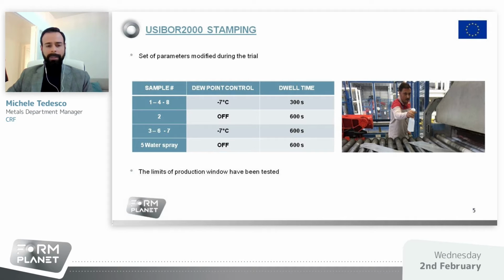component. Based on that, we would like also to test the worst condition that is indicated as number 5, in which we turn off the dew point control in the process. We leave the blank at the maximum time in the oven, and as plus, we sprayed water on the upper side of the blank. This is to test the limit of this material and of our process.